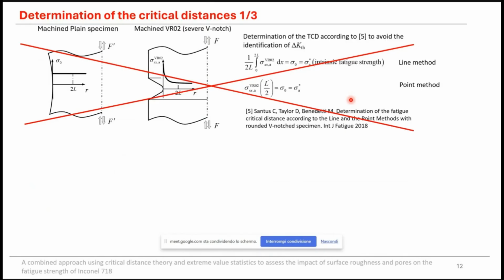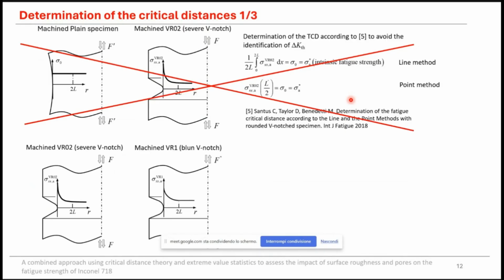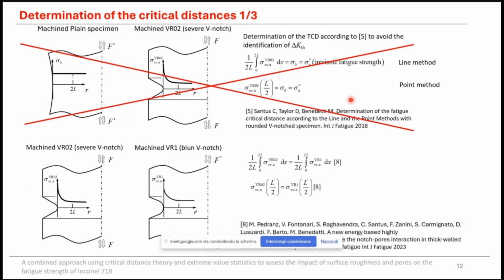of plain machined specimens. As a consequence, we used the double notch inversion, which combines the machined blunt and V-notch specimens. In this case, the intrinsic fatigue strength is an output of the procedure, while in the previous case, it was equal to the fatigue strength of the plain machined specimen. This approach is coherent, for example, with other research groups' fatigue strength analysis of cast iron specimens.